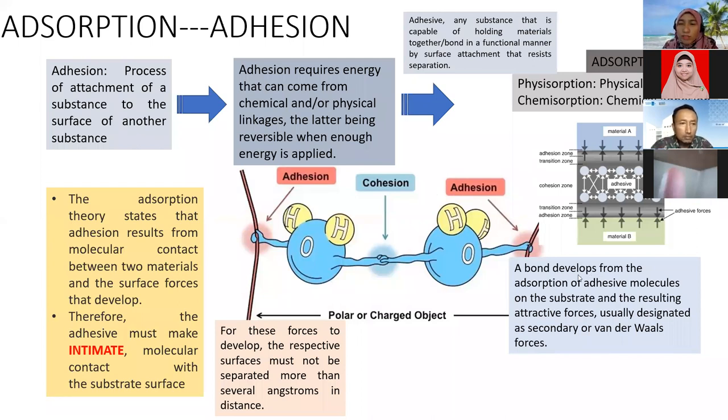A bond developed from the adsorption of adhesive molecules on the substrate and the resulting attractive forces are usually designated as secondary or van der Waals forces. For the forces to develop, the respective surfaces must not be separated by more than several angstroms in distance. So there are terms and conditions for this, just like anything else we do.